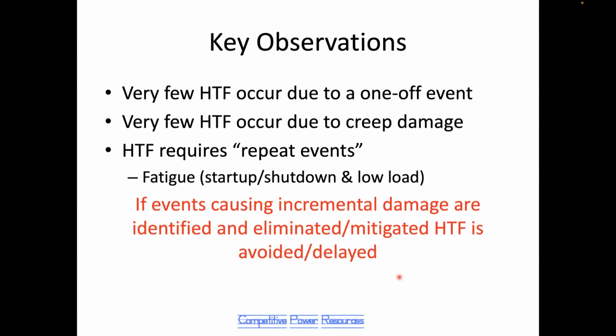Creep damage is operation of the pressure part at a high temperature and at pressure for long periods of time that causes a deterioration of the material properties. That is not a big problem with HRSGs. Fatigue is the principal failure mechanism. Fatigue is generally associated with startup and shutdown of the units and sometimes with low load operation.